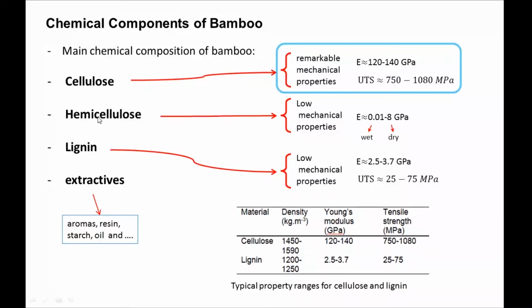And you should know about the cellulose. It has remarkable mechanical properties. The modulus of elasticity is about 120 or 140 gigapascal. It's excellent. And the ultimate tensile strength is about 1,000 megapascal. It's 2 or 3 times more than steel. But hemicellulose is not as resistant as cellulose, and neither is the lignin. The hemicellulose and lignin can only be used as a binder in the structure of the bamboo.